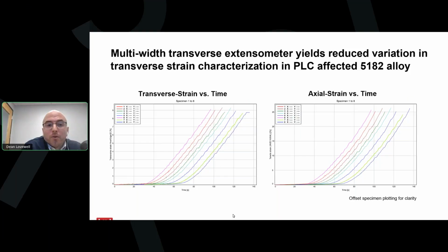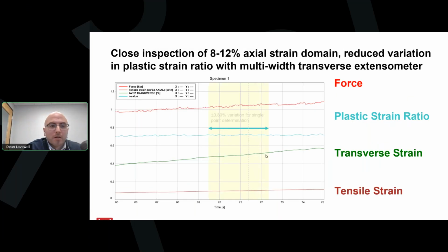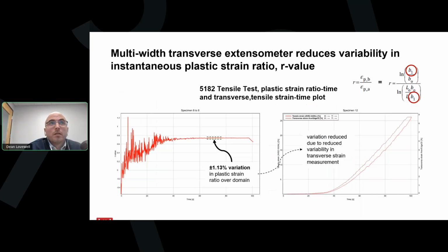Here we see that the plateaus in the transverse data on the plot on the left are significantly shortened because we're now calculating width strain with much greater resolution along the gauge length. Zooming in on the zone relevant to plastic strain ratios calculations, we see much smoother transverse measurement. The variation in R value has dropped across the zone, and now you have a much more reliable indicator for single point R value calculations. Here's a look at R value calculated throughout the test, along with the corresponding transverse and axial strain. Much less variation than with the single point method.